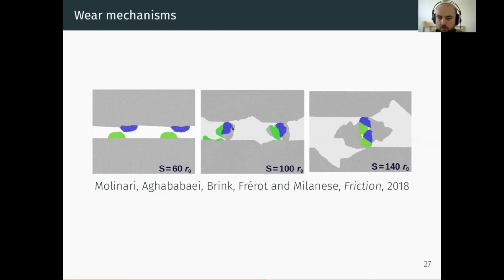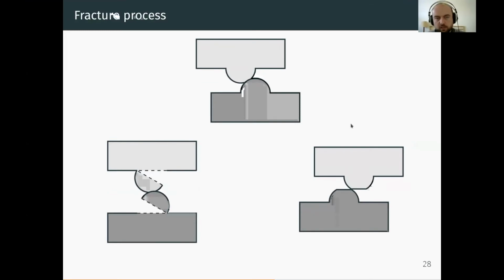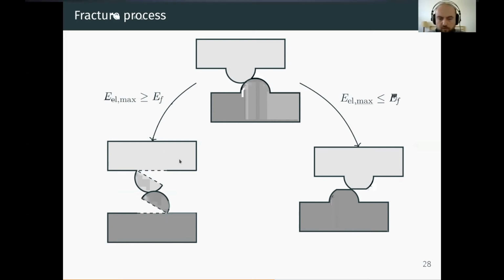If the contact is larger than a critical size, then the adhesive forces that occur at the interface are strong enough so that you can have cracks that propagate in the bulk and detach the asperities. And if you have asperities that are close enough together, you can have crack shielding mechanisms that kick in and allow only a single crack to propagate and detach a single wear debris particle. Essentially, what those studies have shown is that adhesive wear is a fracture process. So if you have enough elastic energy stored in your contact to form new crack surfaces, then you're going to have this brittle mechanism which leads to detachment of a debris particle. And if you don't have enough energy, then you have plastic deformation and the asperities just pass each other and there's no detachment of debris particles.